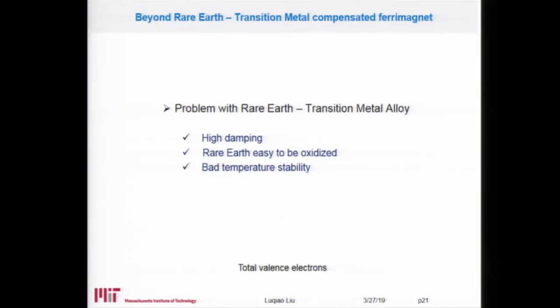Rare earths in the metallic state are very easily oxidized. Even if just simply exposed to air, they will turn into oxide within seconds. Another thing is that they have very bad temperature stability. When you change the temperature, their magnetic properties change significantly, and sometimes it's even irreversible, meaning if you go back to room temperature, they do not keep their original properties. So basically we want to get rid of the rare earth element. So how are we going to do it?